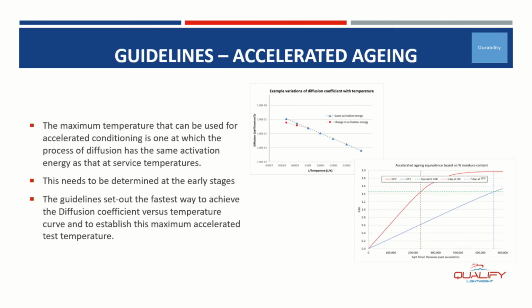There are standard conditioning cycles that could be used, but it's really important to understand what that conditioning cycle is actually replicating and that it's not giving you erroneous results. This graph shows a plot of reciprocal of absolute temperature against log of diffusion coefficient. The gradient of that graph is proportional to the activation energy of the process of diffusion.